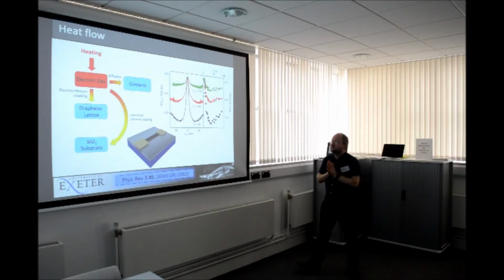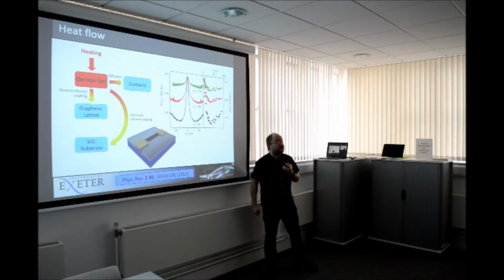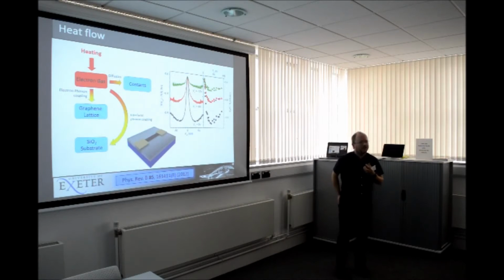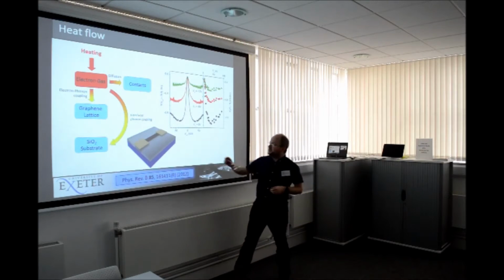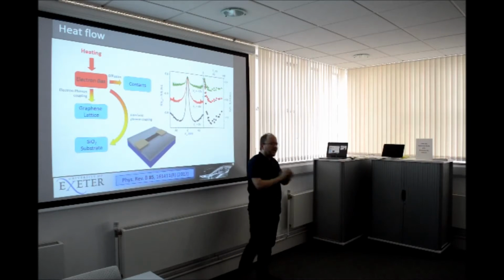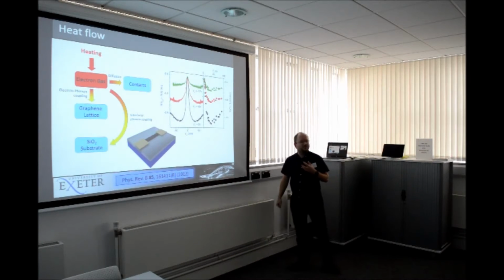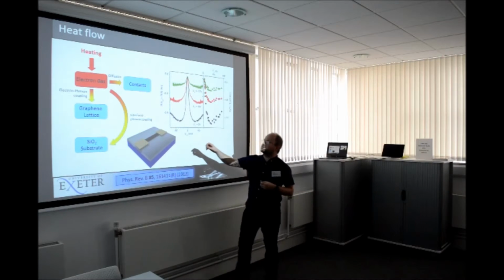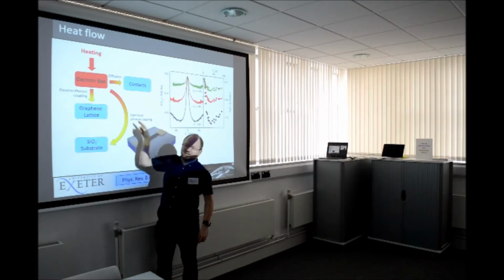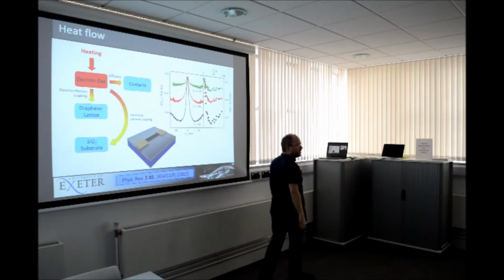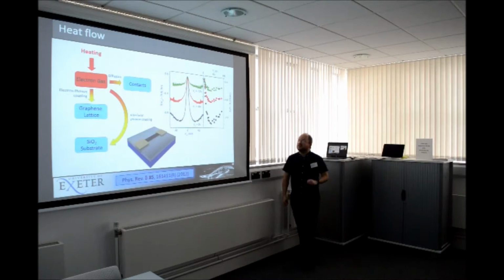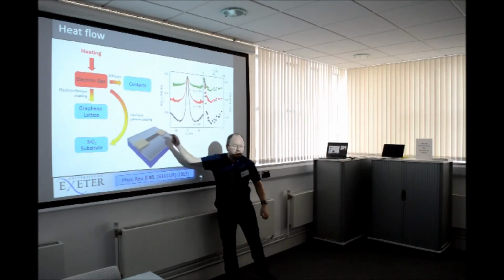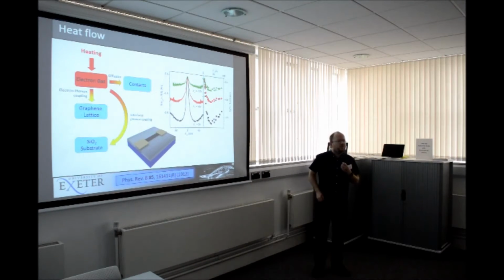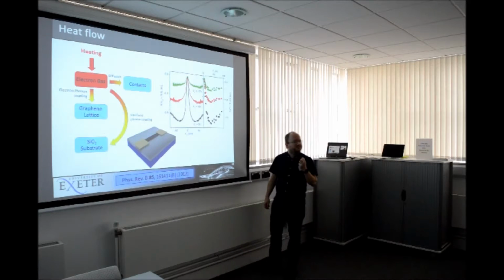We're also looking at heat flow in graphene, so graphene conducts electricity very well. It also conducts heat very well. So this was an experiment designed to look at what happens if you heat the graphene, where does the heat go? And it becomes somewhat of a thermodynamic problem. You have various heat sources, heat sinks, and you can look at ways in which the heat is lost from this device. What you find is that graphene is extremely good thermally in terms of conduction, but very poor in terms of how much heat it can actually hold. It's only one layer of atoms. Of course, it can't hold a lot of heat, so if you put some power into it, it heats up very, very quickly.